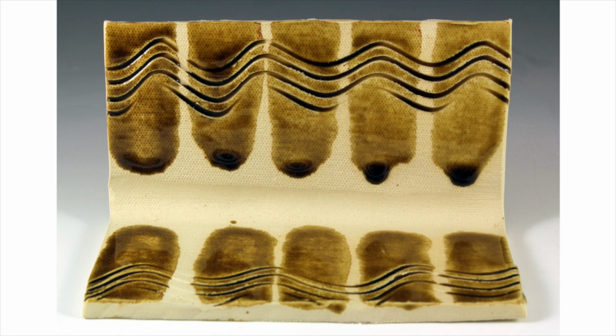To lower the melting temperature of a glossy glaze that has Custer feldspar in it, the first thing you should do is try substituting nepheline syenite, which is a lower melting feldspar, for the Custer feldspar. And then you might want to add a strong low melting flux like Gerstley borate.